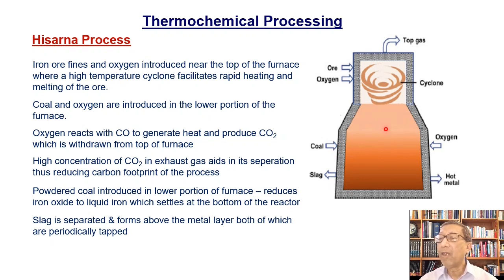Powdered coal is introduced in the lower portion of the furnace, and it reduces iron oxide to liquid iron, which settles at the bottom of the reactor and can be withdrawn from there. And slag is separated from the hot metal by taking advantage of their difference in density. So slag floats on liquid metal and can be very easily separated.